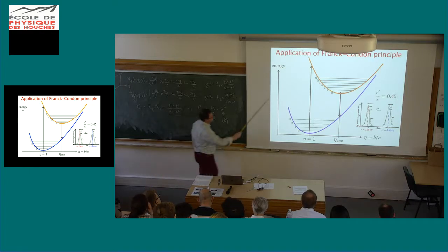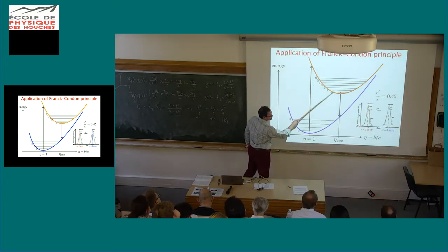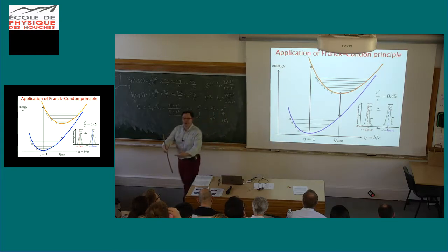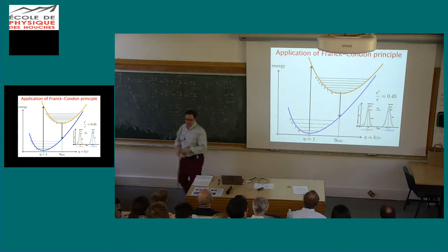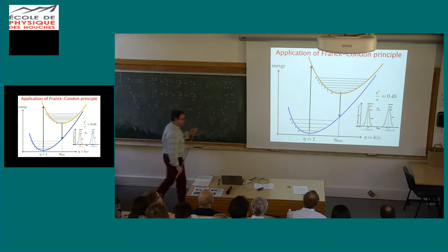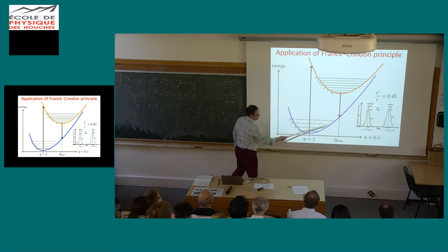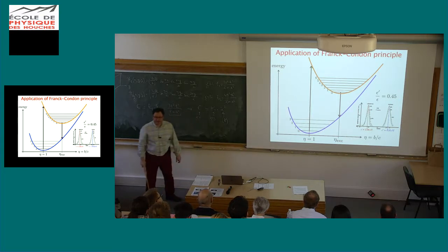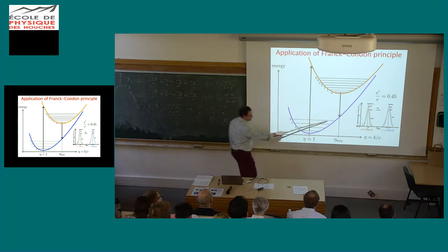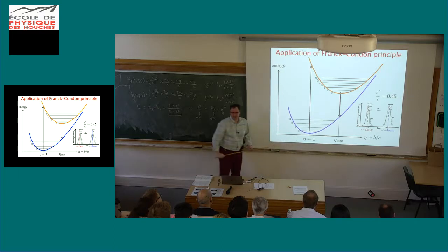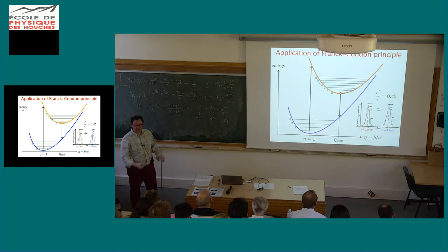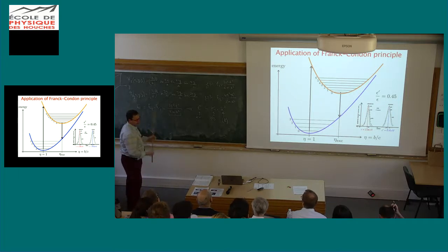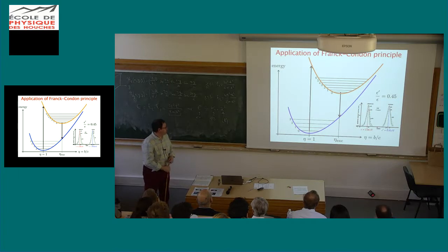There will be a distortion of the crystal, and this relaxation by emission of many phonons ends in the lowest excited phonon level. After, it can decay back to the ground state, and again there is a very quick relaxation by emission of phonons toward the relaxed state where we have, again, this non-distorted box.